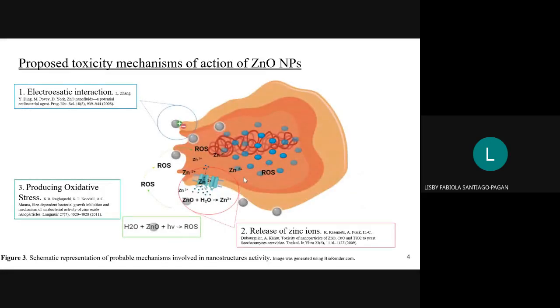Previous studies have shown that zinc oxide nanoparticles hold antibacterial and anticancer activity, but the exact mechanism of toxicity is still under debate. What is of general consensus is that zinc oxide nanoparticles can exert their toxicity by causing damage in the outer membrane of bacteria and producing reactive oxygen species. In this image, I present three examples of the most common mechanisms proposed. The first one is damage through electrostatic interactions.